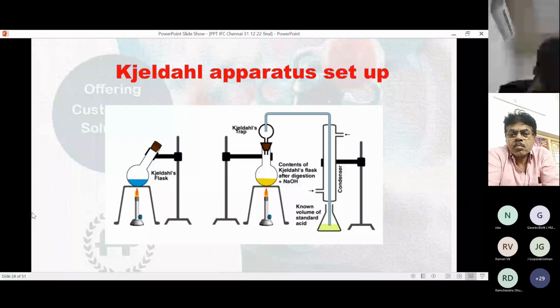Then sulfur content. Sulfur content is also a very integrated test, and many of the research laboratories have an analyzer called CHNS. These elemental analyzers are there in different IITs, but my experience of getting samples analyzed at this low value of sulfur is not very good. I had given the sample to 2 laboratories, and results are far from the reality in my standard sample also. So in our laboratory, we have tried to develop a test, and we have seen that results are fairly accurate. I will tell you the theory only, and we have the calculation that you can go through afterwards leisurely.